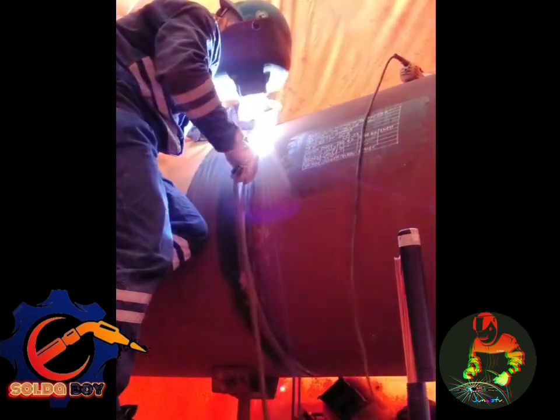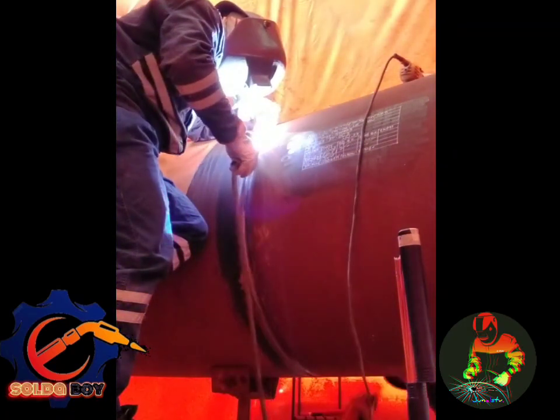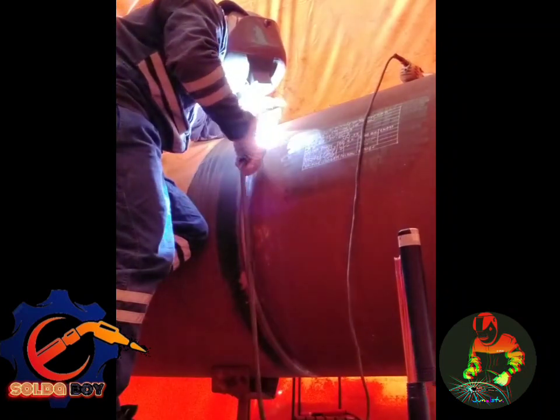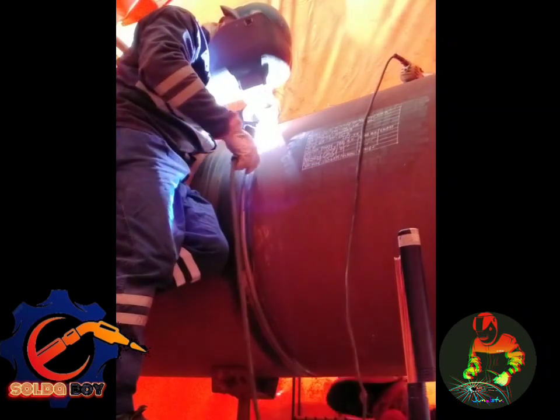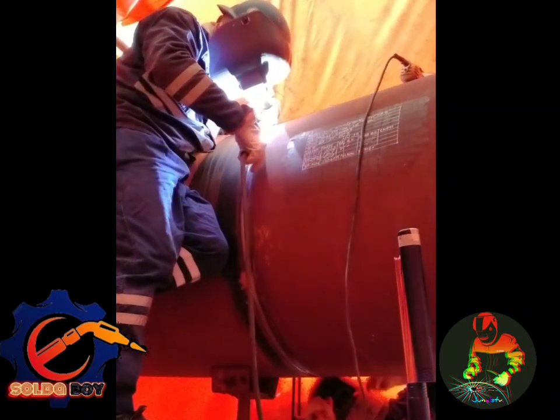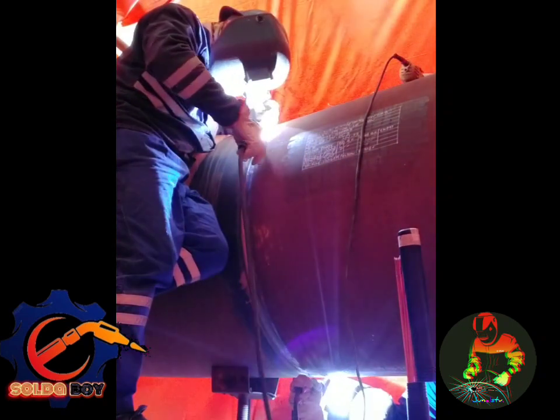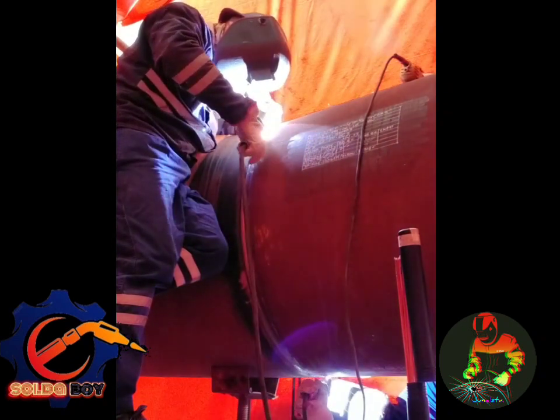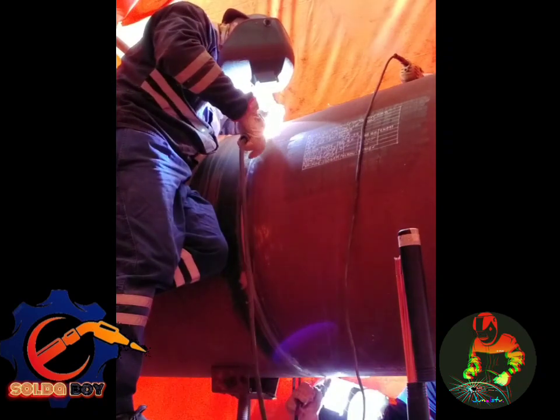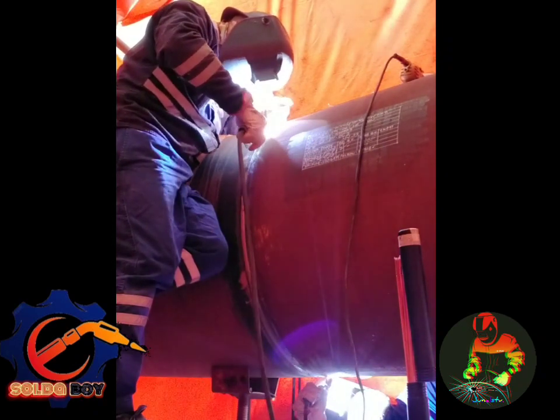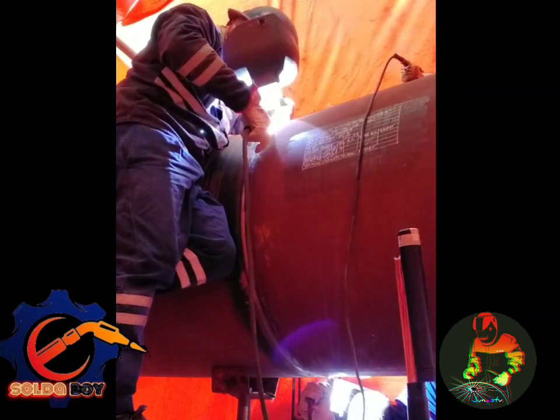The idea of the hot pass includes helping to push out root passes that may have some suckback, because as the weld progresses, a true hot pass makes the thin root pass become molten again and sink down. This sinking down actually forces the bottom of the root pass out a little further.